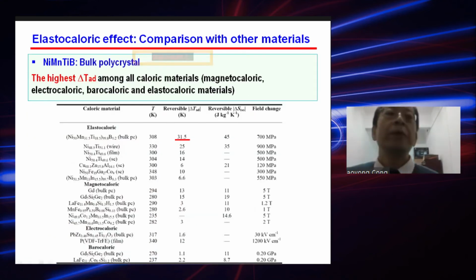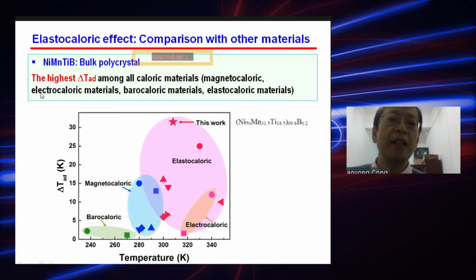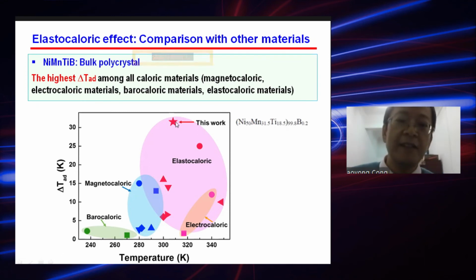We also compared with other materials, and we find that our sample shows the best elastocaloric performance among all elastocaloric materials, no matter whether in bulk, wire, thin film forms or in other forms. We also compared the temperature change with other caloric materials, including magnetocaloric, electrocaloric, and barocaloric materials. It should be mentioned that here we only compare the adiabatic temperature change that is directly experimentally measured. We did not consider the values obtained indirectly or quasi-directly. And this is the position of our adiabatic temperature change, and we find that it is the highest adiabatic temperature change among all caloric materials.